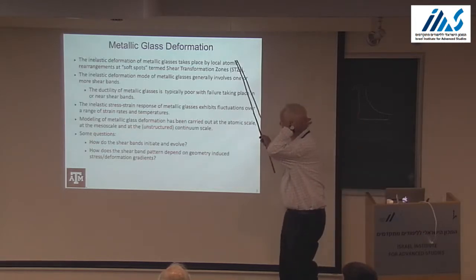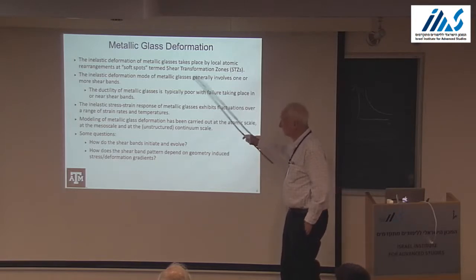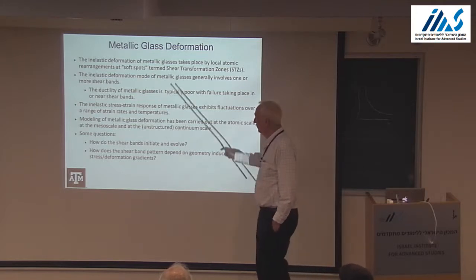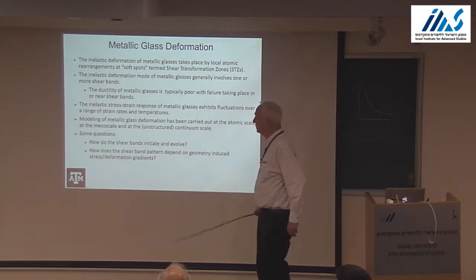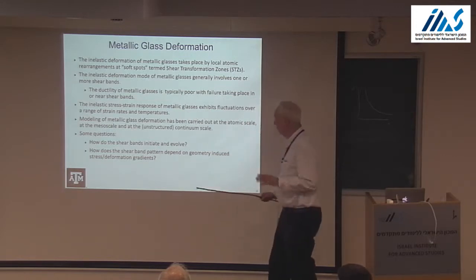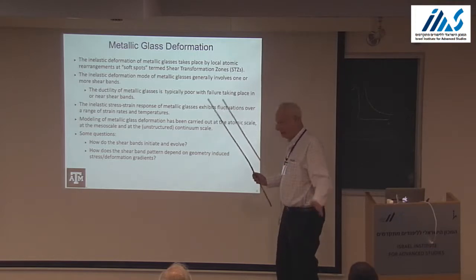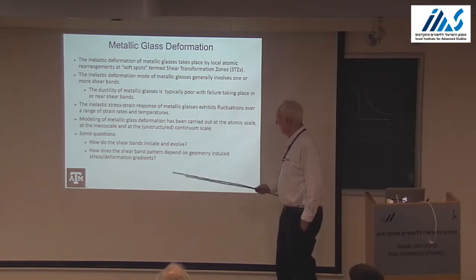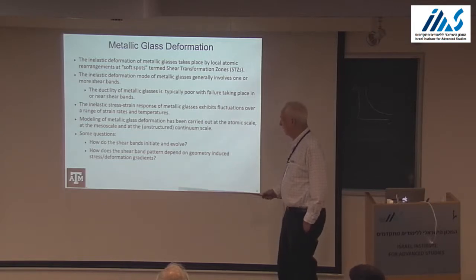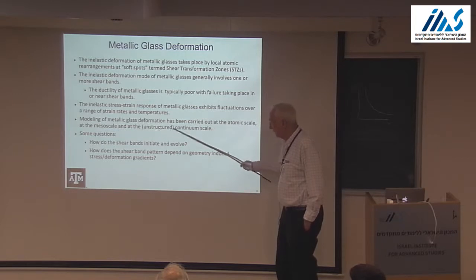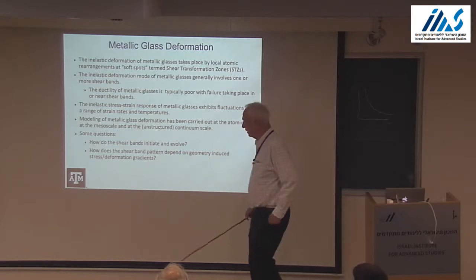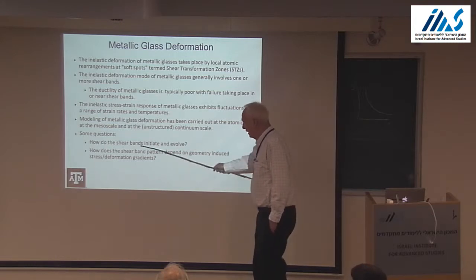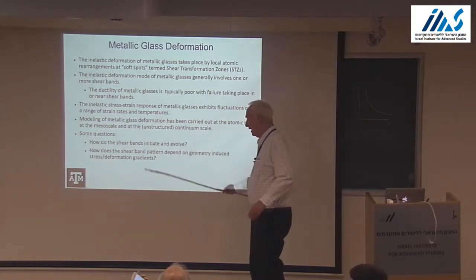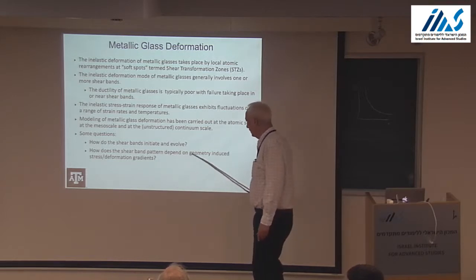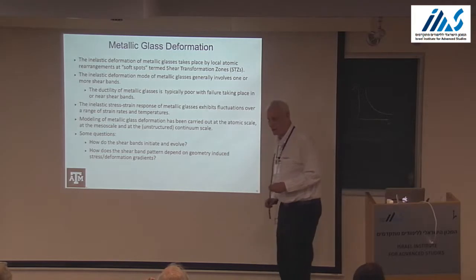Okay, so it takes place by local atomic rearrangements or soft spots, termed shear transformation zones in some communities. It generally involves one or more shear bands. Ductility is typically poor, failure taking place in or near the shear bands. It exhibits these fluctuations, and a lot of modeling work has been carried out at the atomic scale, mesoscale, and also at the continuum scale. Questions I'm going to try and look at are: how do the shear bands initiate and evolve? And how does the shear band pattern depend on geometry, including stress and deformation gradients?